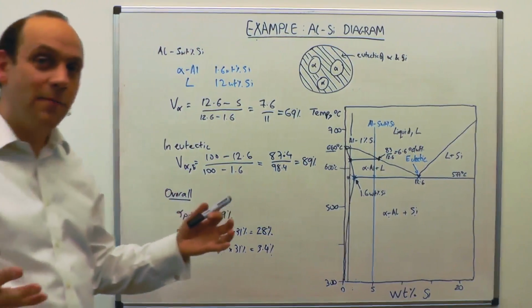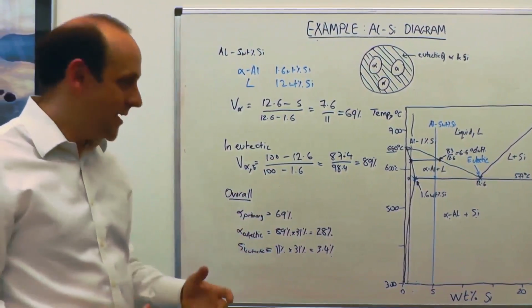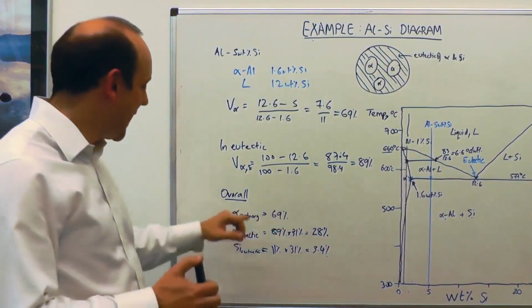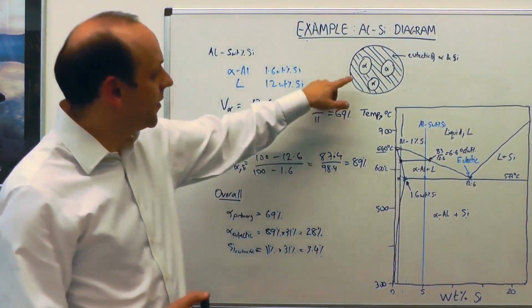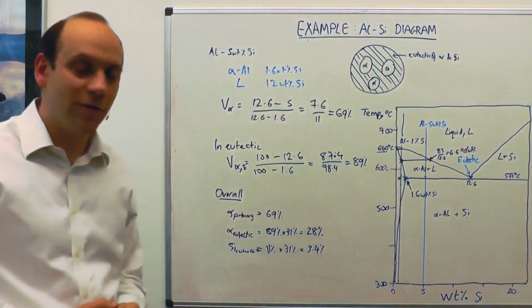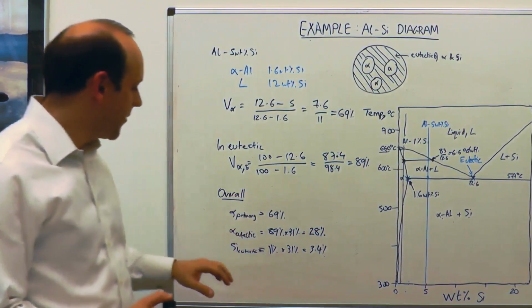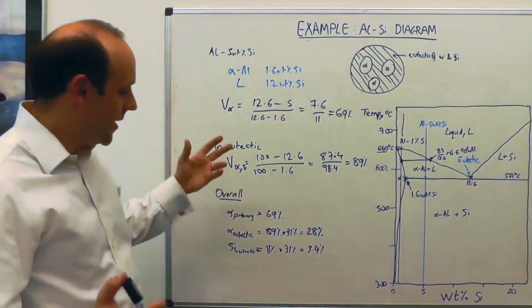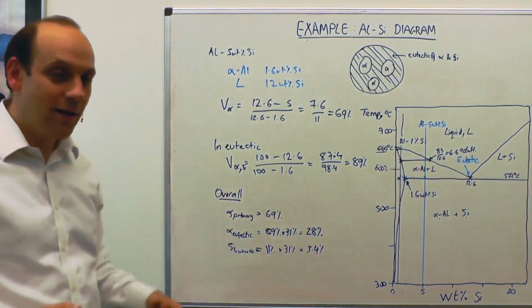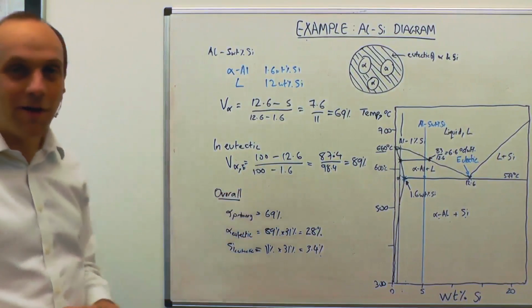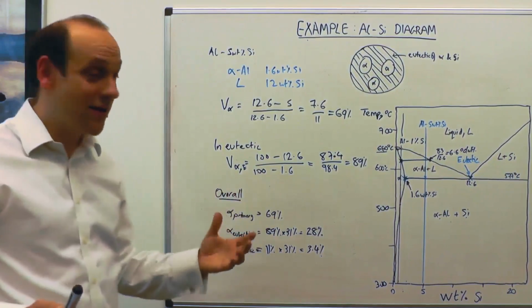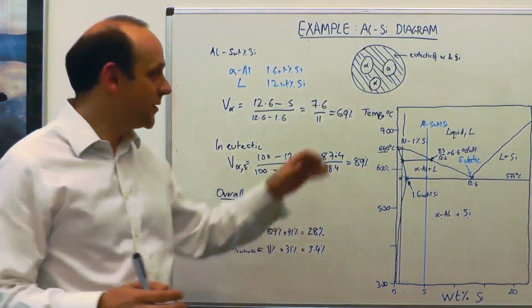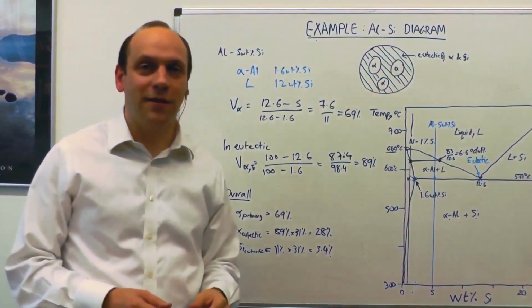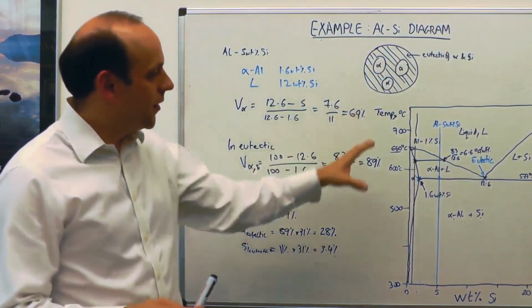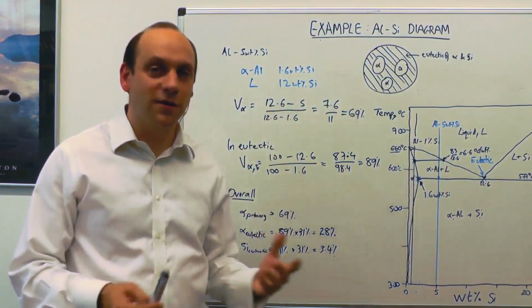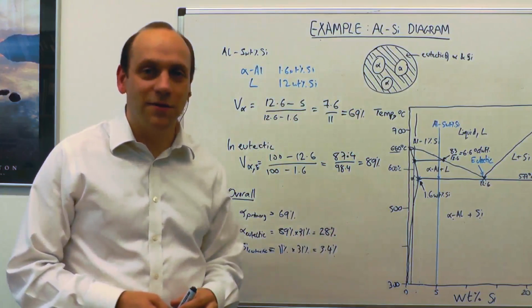So when you see the term microstructural constituents in a question, what it means is both the phases and the forms in which they occur. So for the alpha, whether it's primary alpha crystals or alpha in the eutectic. If you just said to me, the total amount of alpha from the lever rule is 97%, and the total amount of silicon, I'd give you partial credit. You've shown me you know how to use the lever rule, but you haven't demonstrated that you understand how to divide it into constituents, that is, this primary alpha and alpha in the eutectic there. And so that's a quick whiz round the sorts of questions that you can ask with phase diagrams and answer using them, and the sorts of calculations you can do.